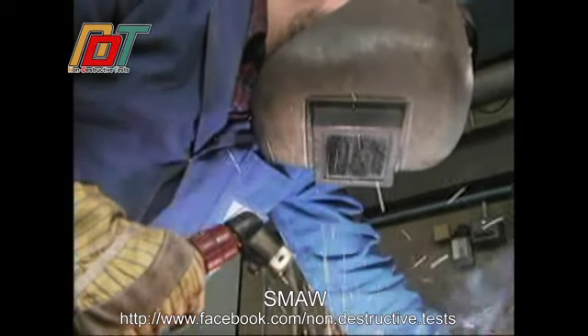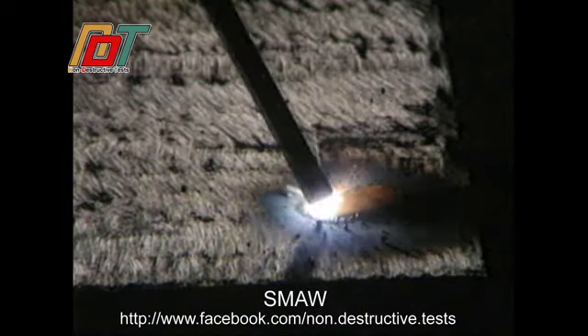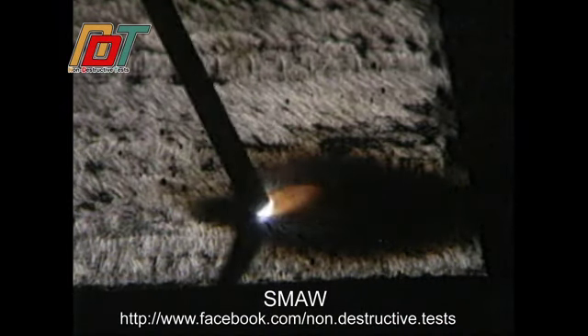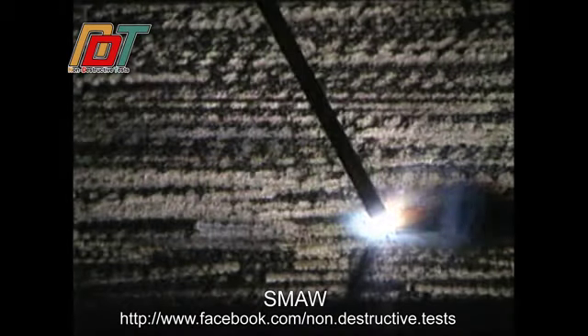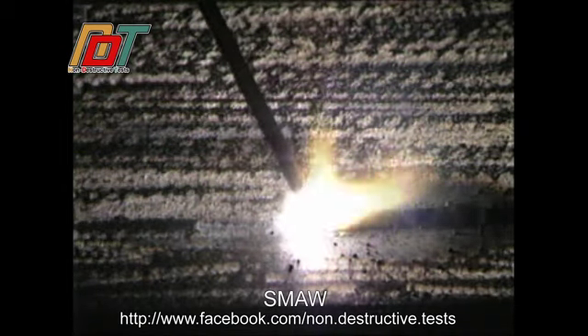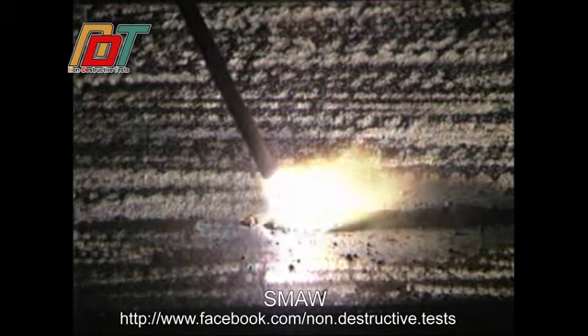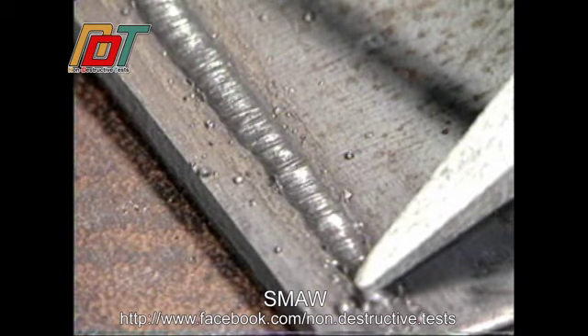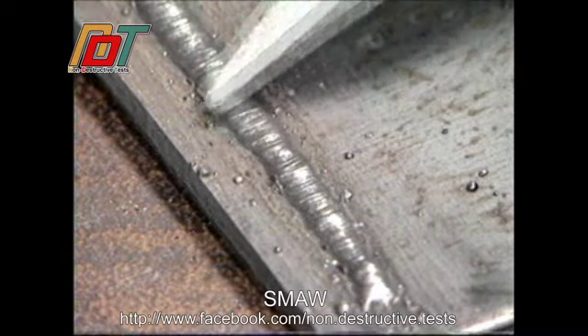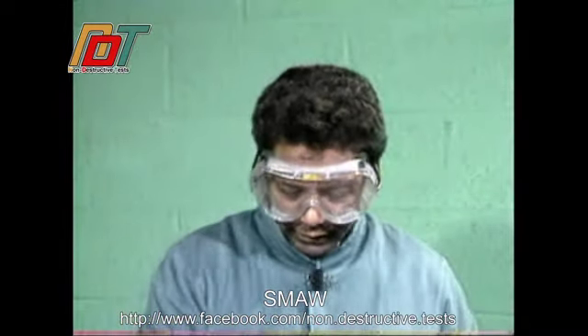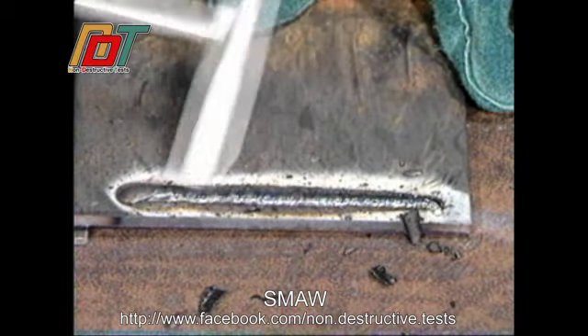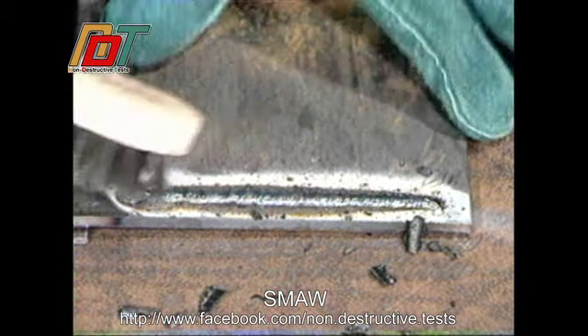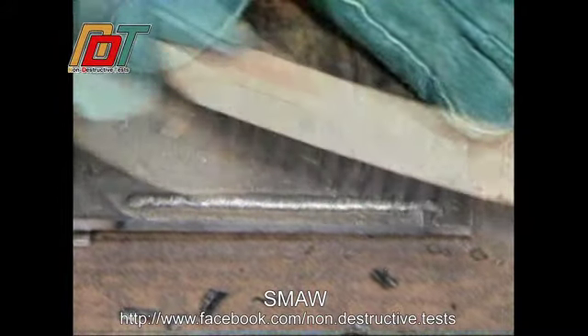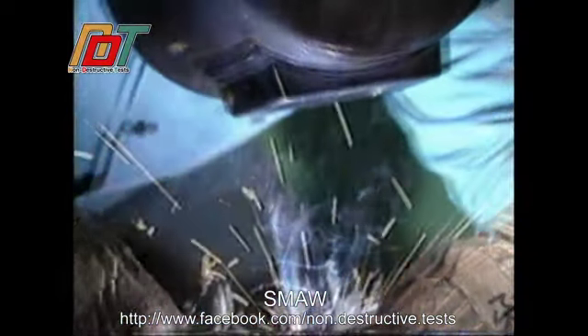Too short an arc will be erratic and may short-circuit during metal transfer. Too long an arc will lack direction and intensity, which will tend to spatter the molten metal as it moves from the electrode to the weld. The spatter may be heavy and deposition efficiency low. Also, the gas and flux generated by the covering are not as effective in shielding the arc and the weld metal from air. The poor shielding can cause porosity and contamination of the weld metal by oxygen or nitrogen, or both, and the quality of the weld will be poor.